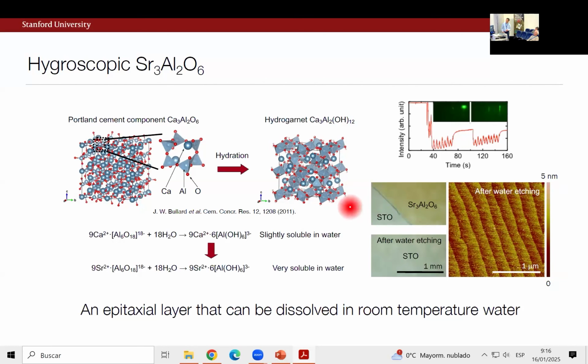And in terms of thin film growth, this very complicated looking system grows rather straightforwardly and nicely. So first thing I can say is that even at the very earliest stages, you could see unit cell by unit cell growth. This is looking at surface electron diffraction to monitor that deposition process. I should say that these are not unit cells, actually. It's these quarter unit cell charge neutral units that are being deposited here.